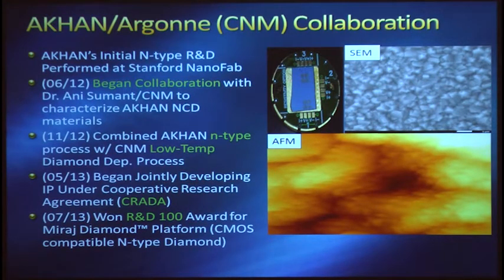Very shortly thereafter, we began developing this technology cooperatively to bring it to market. And shortly after that, we won the 2013 R&D 100 award for it because of its magnitude and the long-standing issues in diamond. Here we can see on the right, via the atomic force microscope image, that at the nanoscale, there are no more of these pits. Rather, we have these protruding aggregates, so it didn't adversely affect the electronic performance of this diamond material.